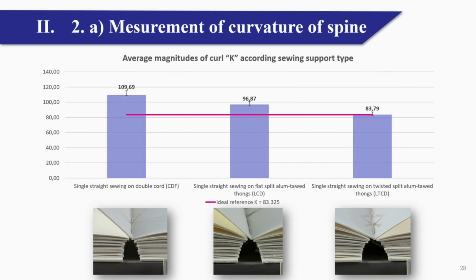The results are according to the sewing supports. Twisting thong provides the widest arc, closest to the reference value. The flat split thongs have a slightly narrower arc, but also quite close to the reference value. Finally, the linen cord produces the narrowest and highest arc. As previously, quantitative data are correlated with the visuals of the photography protocol below.